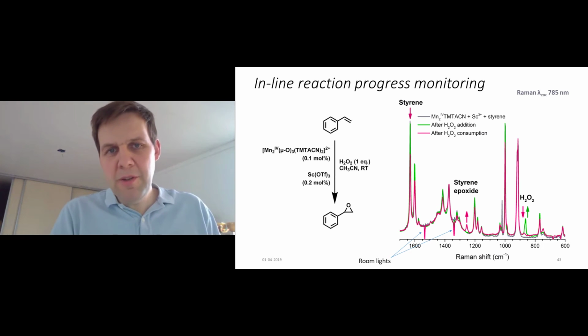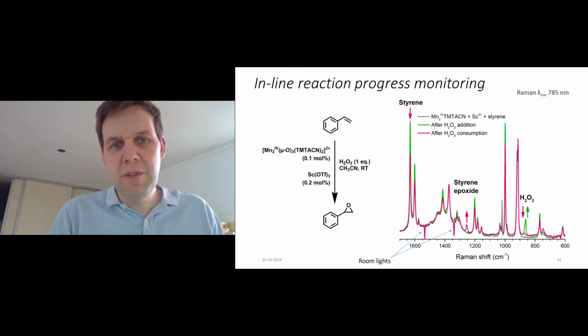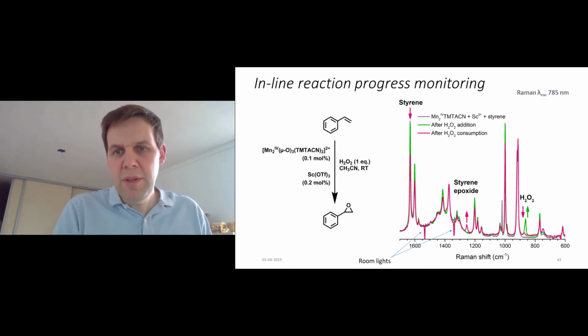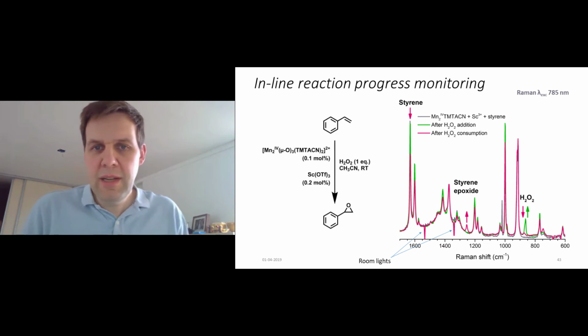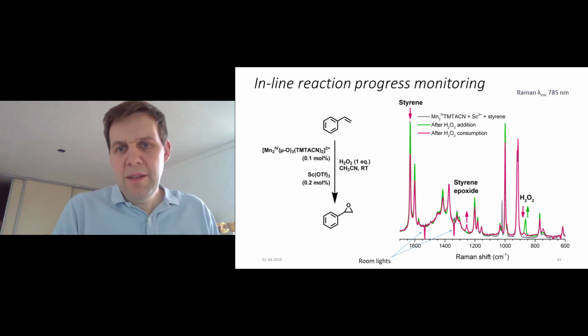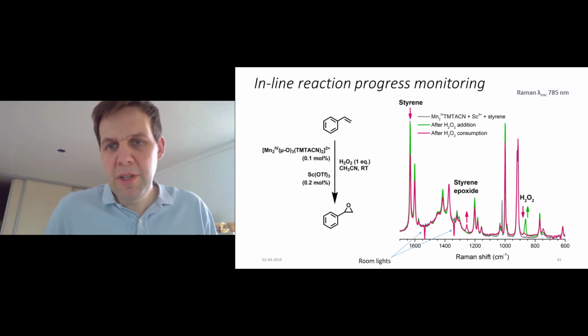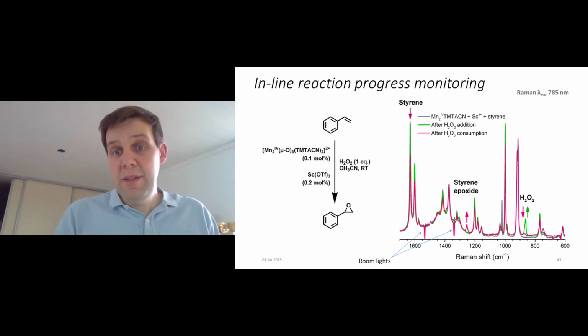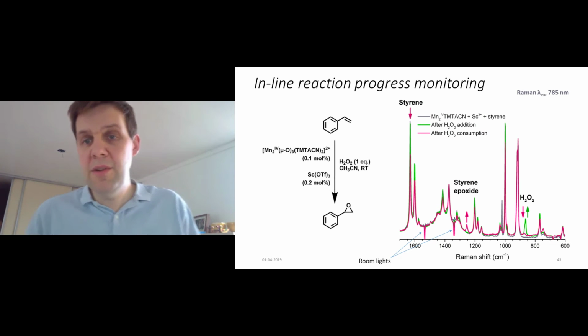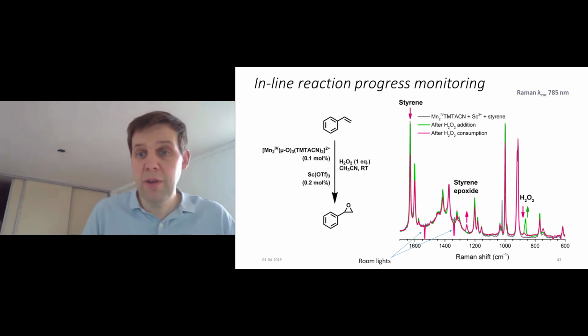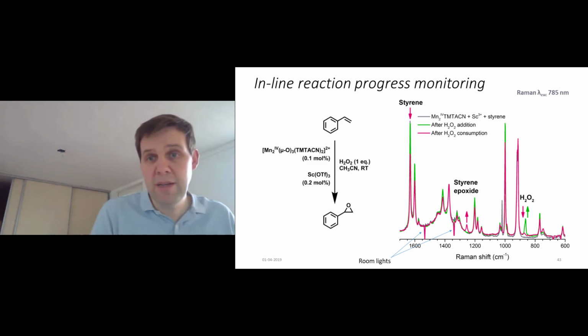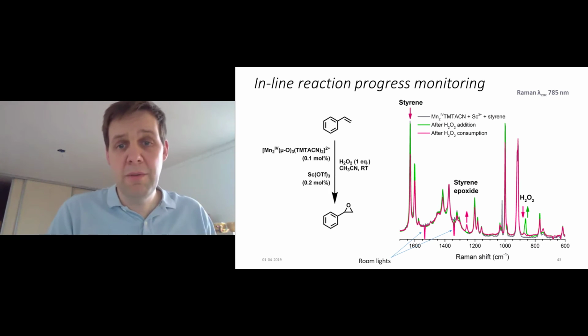So this is a Raman spectrum of a solution of styrene, which is going to be converted to epoxide with this catalyst and scandium present. And we have hydrogen peroxide. This is just a Raman spectrum at 785 nanometers. What you can see at around 1600 wave numbers is the bands from styrene, which are decreasing. That allows you to look at conversion. And the band at around 1260, with an arrow pointing up, is from the styrene epoxide. We can see the epoxide formation. And at around 870, you can actually see the band from hydrogen peroxide. So you can follow the hydrogen peroxide appearing and disappearing. When you add it, it goes up and then it disappears over the reaction.